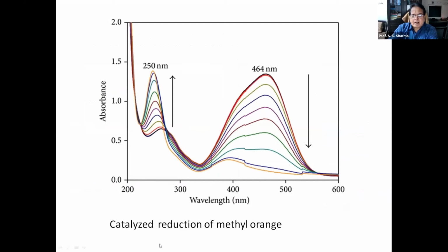So this is again a catalyzed reduction of methyl orange. So you say using some catalysis. The methyl orange, that is a dye, a very commonly used dye. So with time, you see the peak at 250 nanometer goes up, and the peak at 464 nanometer goes down. And this graph you can generate using a UV visible spectrometer. So that gives you an idea what is happening to the chemical with time.